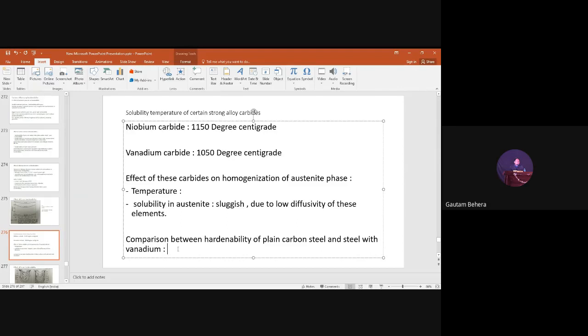In the earlier part, we have seen if we have a plain carbon steel, that means alloying elements are absent, the nose of the TTT curve will not move towards the right, so hardenability will be poor. Already we have discussed that. And again, we have discussed here vanadium is there. Vanadium forms strong carbides, which are not easily soluble. And if it will be soluble, homogenization will not be easier, it will take time. So hardenability will be poor. So now there is a very good confusion between them. So how can you compare this? Where can you get high hardenability, where can you get low hardenability, or will you get the same hardenability?